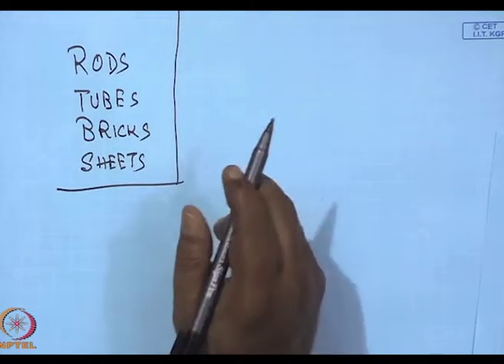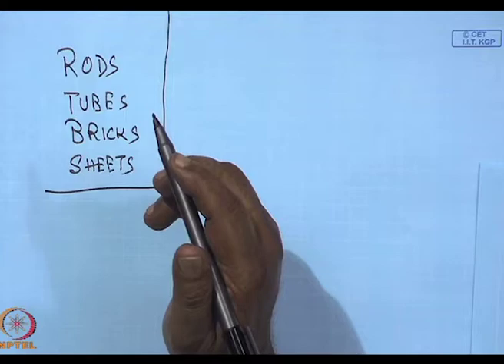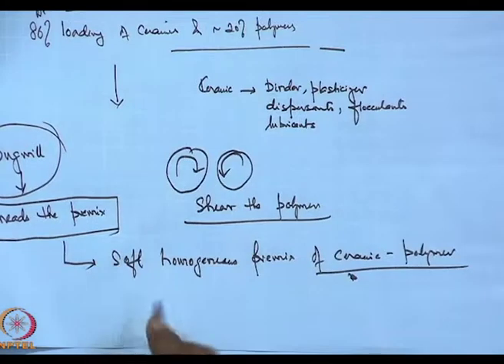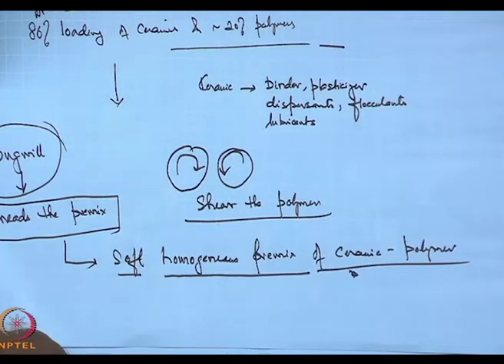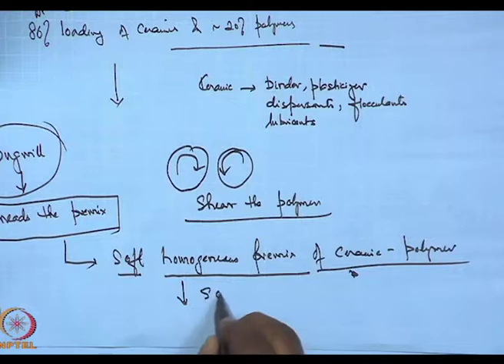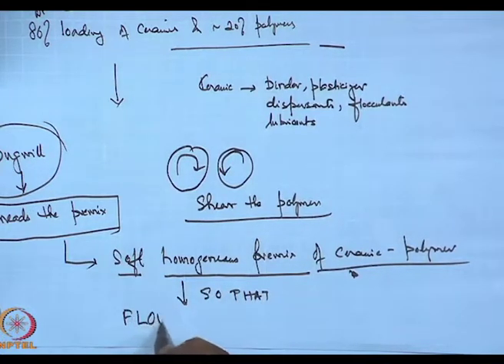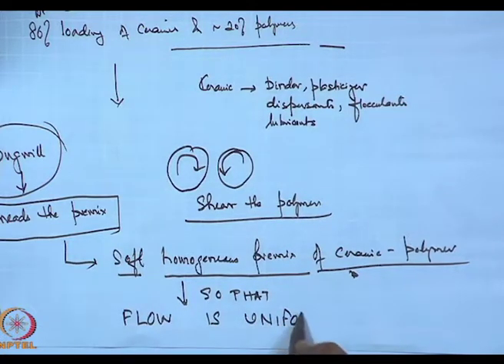As I said, due to the heavy ceramic loading, mixing of the ceramic with the polymer is a problem. Abrasion is a problem because the ceramics can abrade, and hence we have to be very careful when we extrude a ceramic. Now, let us take a couple of issues during extrusions. What can be the issues that may cause a problem? One is that I had written over here soft homogeneous premix. Why? So that flow is uniform from the nozzle.